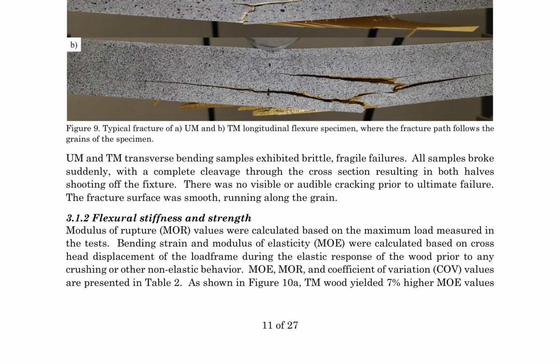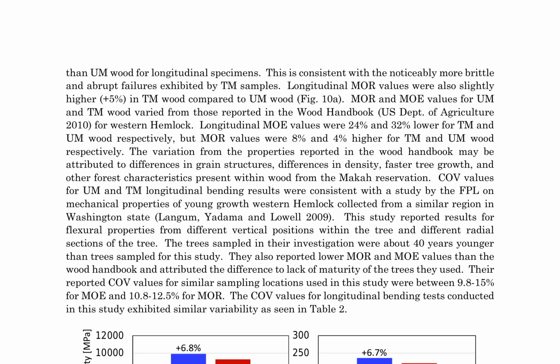Transverse bending tests showed that both TM and unmodified samples failed in a brittle, fragile manner, with sudden and complete cleavage through the cross-section. The fracture surface was smooth following the grain. The MOR and MOE values for transverse bending tests are presented in Table 2. TM wood exhibited lowered transverse strength and slightly lowered transverse stiffness compared to unmodified wood.